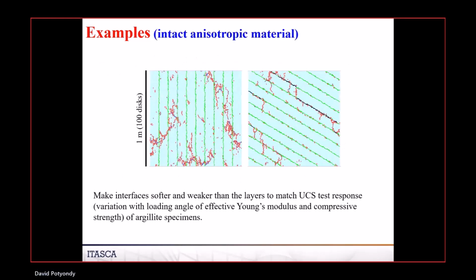Here we wanted to see if we could construct a rock that was transversely anisotropic. So we bond these things together. We put in these joints by means of the smooth joints, and then we do UCS tests that are oriented at different angles with respect to this. So this test is loading this way, this test is loading this way. It's at a different angle with respect to all those little joints that are in there. We make those interfaces softer and weaker than the layer material, and then we see these different failure mechanisms. When it's at an angle, when you reach the peak, it's failing because you're triggering sliding along these interfaces. When it's like this, you don't get sliding. It's just the intact part of the system that has to fail.